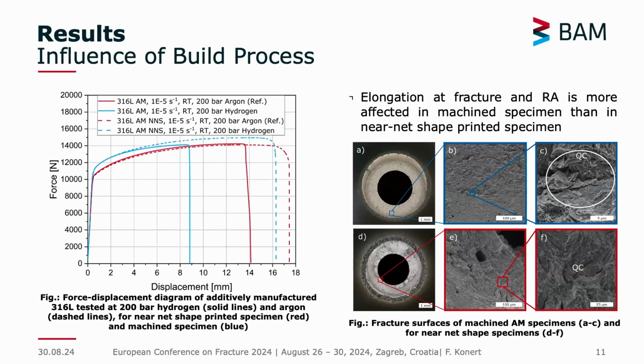On the one hand, as I just said, we have specimens that were printed as cylindrical bars, and afterwards we produce our contour conventionally, and we also have specimens which are printed near net shape. The red ones are the printed near net shape, and the blue ones are the machined samples.